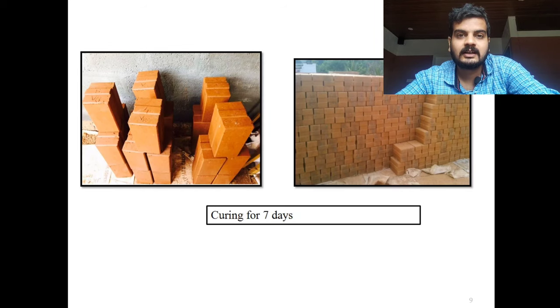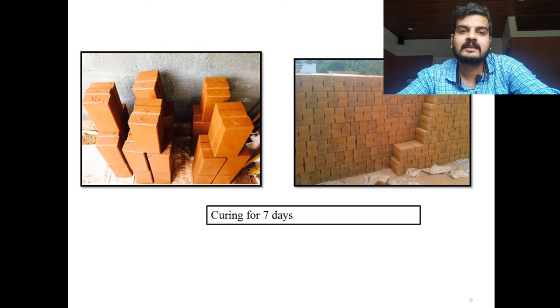Curing means the bricks after casting should be kept under shade and should not be exposed to sunlight, because the moisture should not escape from these bricks. This kind of curing is followed, and a minimum of 7 days curing is required. But if we go for more curing days, like 7 to 14 or 14 to 28, the strength will be increasing. As I have tested some of the bricks, there's a gradual increase in the strength when we go for more curing days.